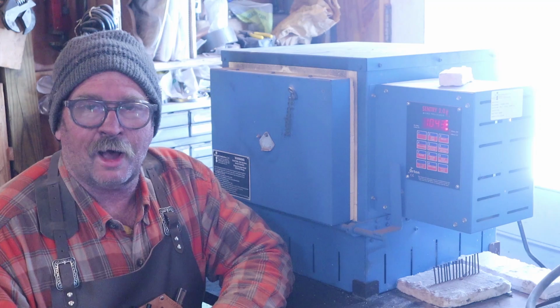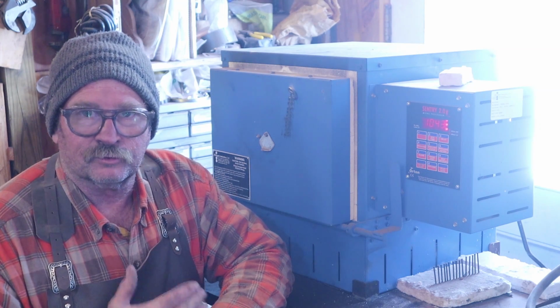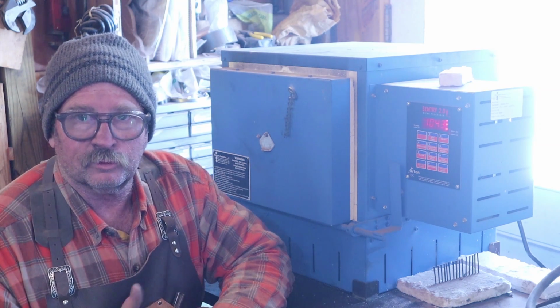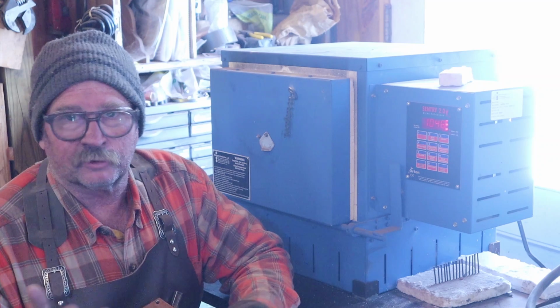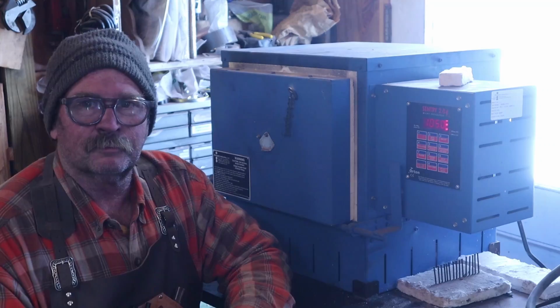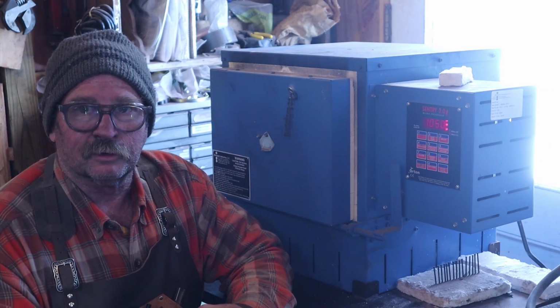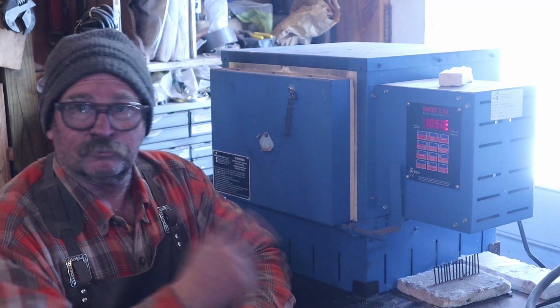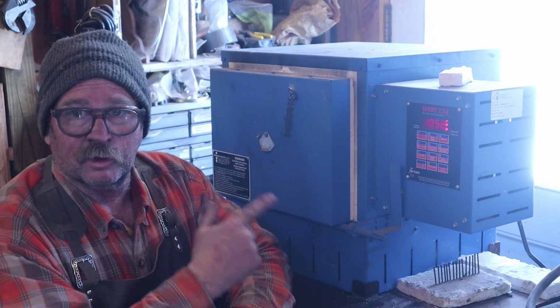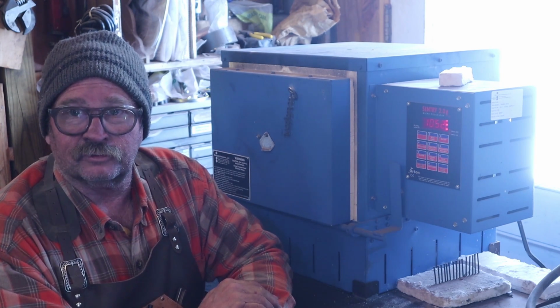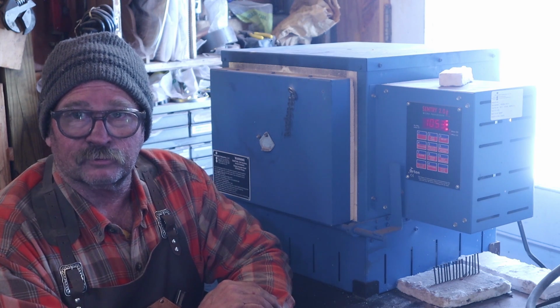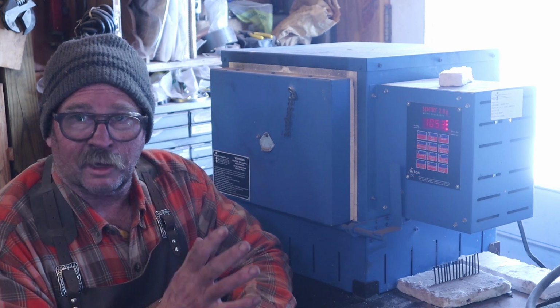Wire brushing things hot like that really gets all the scale off, leaves a very nice smooth finish, depending on scratch marks, hammer marks, things like that, of course. But I think it will make a nicer looking product in the long run. I took them still hot from wire brushing. I put them in the heat treat oven. I've got this set to soak at 1200 degrees for 20 minutes. Get them nice and evenly hot.